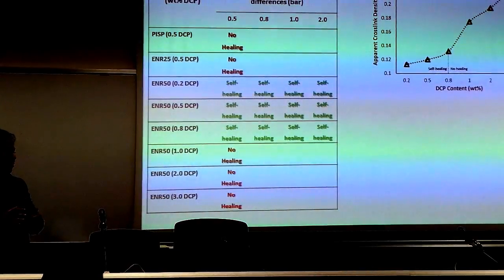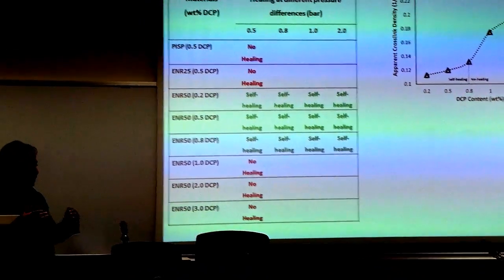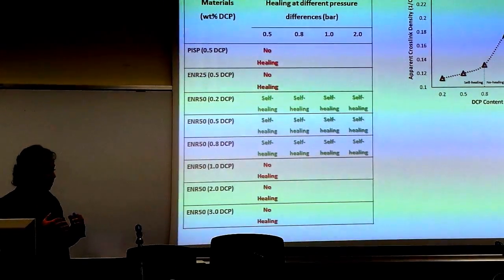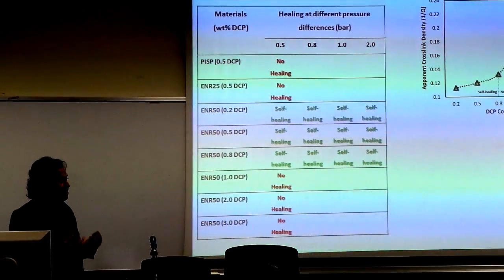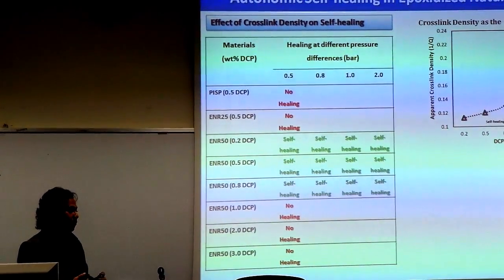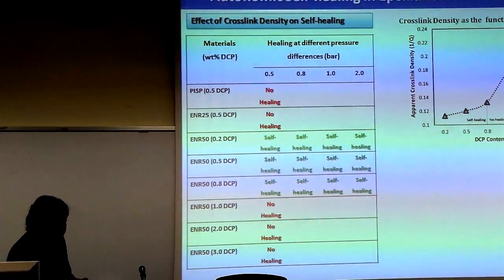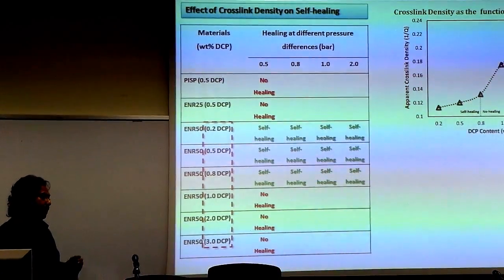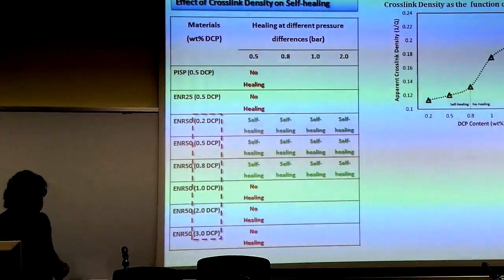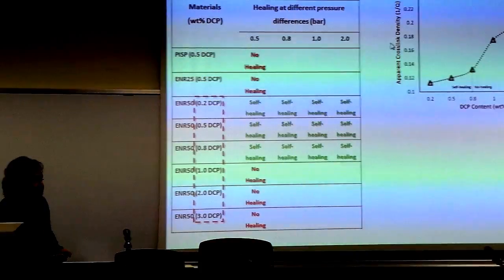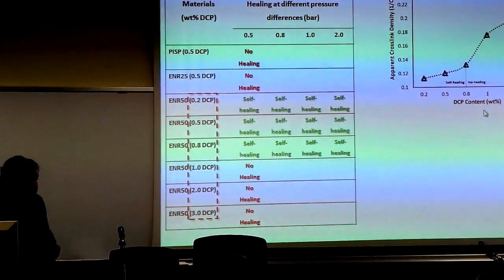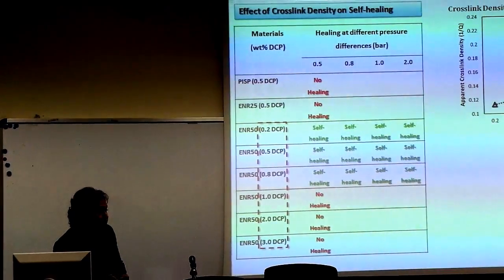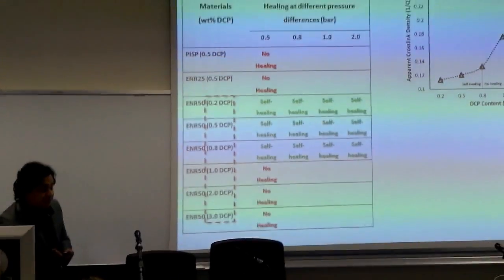Since this interdiffusion behavior is largely influenced by the mobility of macromolecular segments in rubber, I tried to understand the effect of the crosslink density of rubber on their self-healing. So I vulcanized the rubber with different amounts of dicumyl peroxide. As you can see in this plot, the crosslink density of rubber is a function of dicumyl peroxide content. As we increase the dicumyl peroxide content, the crosslink density increased.